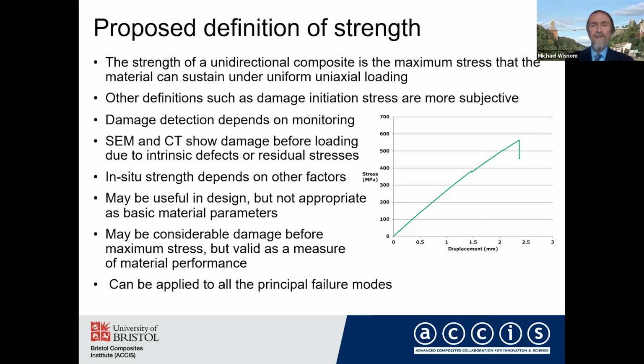be using. Now, if we do take that final ultimate strength as the parameter, then there may be considerable damage, but I think it's still valid as a measure of the ultimate material performance. And this can be applied to all the principal failure modes: tension, compression, both in the fiber direction and transverse and shear. And I guess what it really comes down to here is why do we want to define strength?